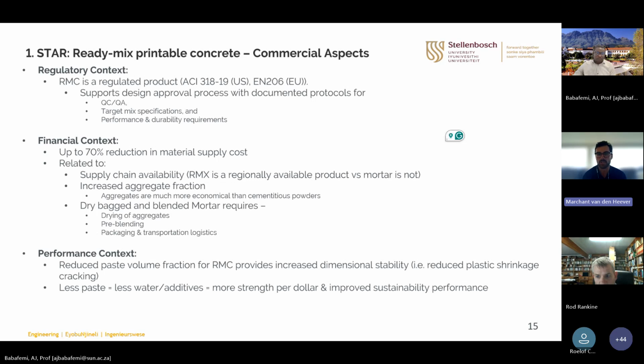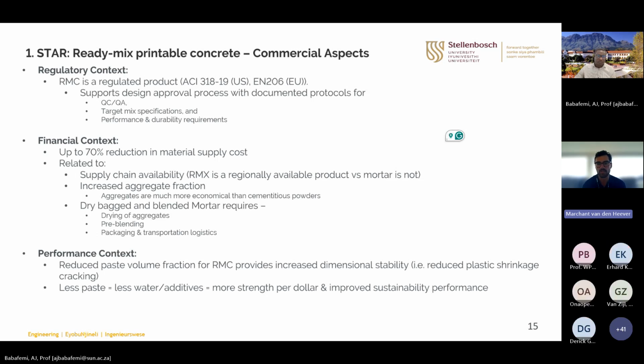From a financial context, we're able to reduce the cost by about 70%. And this is by and large related to the supply chain availability. So ready-mix is a regionally available product where mortars are not. We're able to leverage increased aggregate fractions, and putting this in a financial context, aggregates are much more economical than cementitious powders. So from that perspective, it's a no-brainer to move to ready-mix printable concrete. And then the final aspect is that dry bagged or pre-blended mortars require some logistical considerations in the sense that you need to dry these aggregates, so there is cost and energy involved. It also requires pre-blending, and it requires packaging and transportation logistics, as John had pointed out for the previous study that had been conducted.